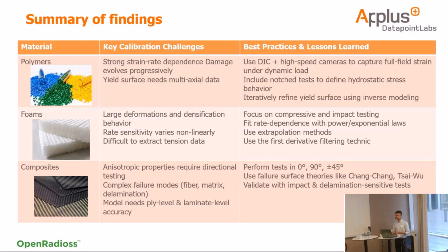We have a really huge amount of data available, and we could avoid guessing what's happening with the polymer under some conditions, because this is a big problem when simulating or calibrating models for polymers: they change behavior from ductile to brittle, and from brittle to ductile, really fast. If you don't have the data available, it's impossible to guess and calibrate a good model, and then when you apply it to your own applications, you may say this model is not working. That's because we are missing some of the data, so we didn't calibrate the material card properly.